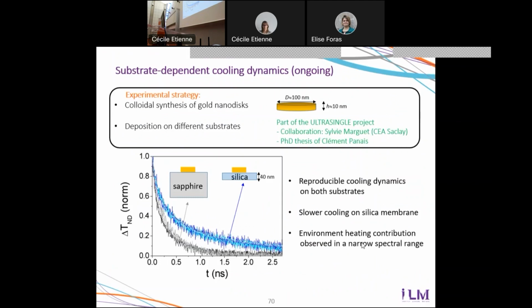Okay, just before finishing, this is to give you a flavor of a very recent experiment that we are now performing with disks produced by chemistry. The good thing of such a chemistry production is that we can deposit the disk on the substrates that we want. In particular, we could deposit the disk on very thin membranes. And here, what we found was that the cooling becomes much slower when the disks stand on a thin membrane. It's because the silica that we used does not conduct heat as efficiently as sapphire, but it's also because heat spreading is limited on a thin membrane, because it will mostly be diffusion in 2 dimensions instead of 3 dimensions, so it's less efficient. So the disk takes longer to cool down.